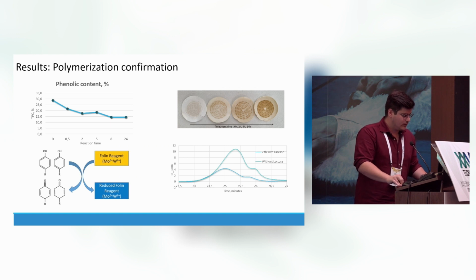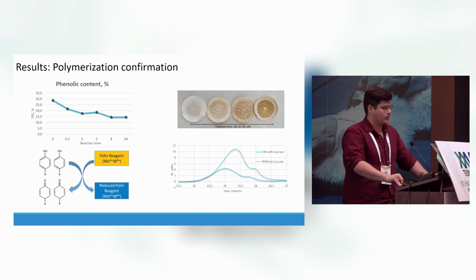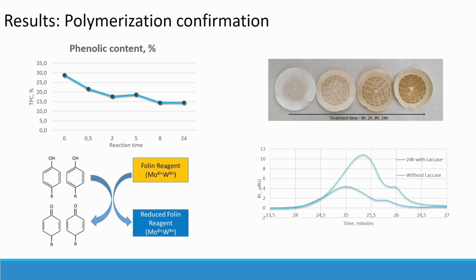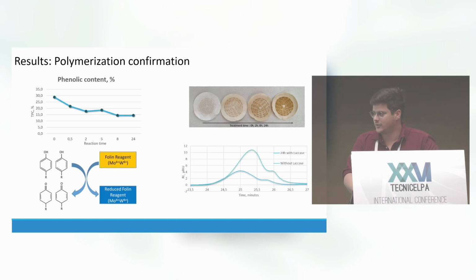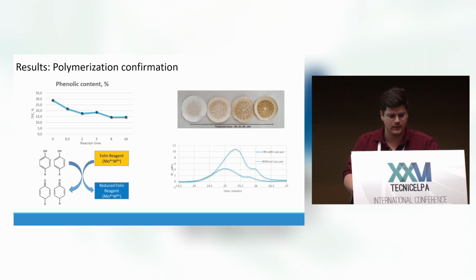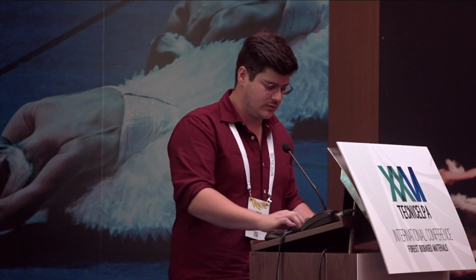Regarding the phenolic content, as I mentioned before, it analyzes the hydroxyl groups of our material. And we can see that with the treatment time, it decreases. By this means, with the LACCASE treatment, we achieve denser structures and higher molecular weight. The figures are just a more visible example of the polymerization that we achieve.